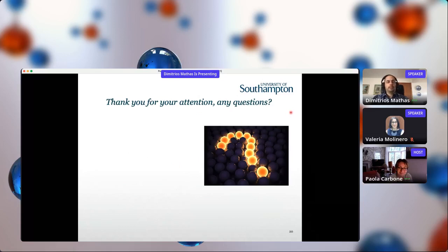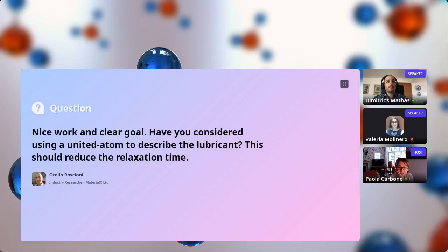Thank you very much, Dimitrios. Very nice talk. There is one question from Otello Roscioni, but I also have a very quick one. One of the ways that we use to reduce the problem of slow relaxation of the pressure tensor is to use the Einstein relationship, where rather than the autocorrelation function of the pressure, you use basically the velocities. That should speed up the convergence a bit. I wonder if you have explored this.